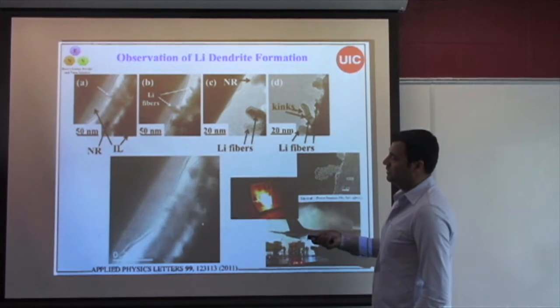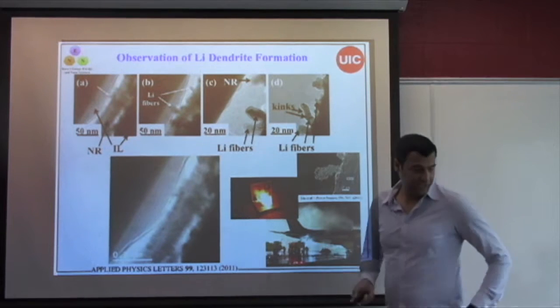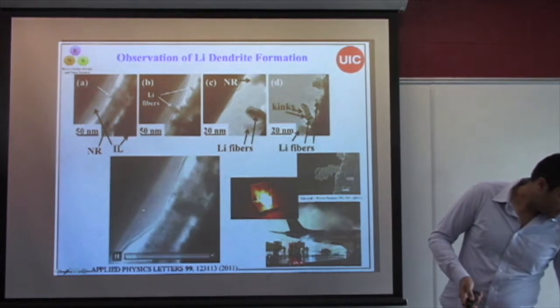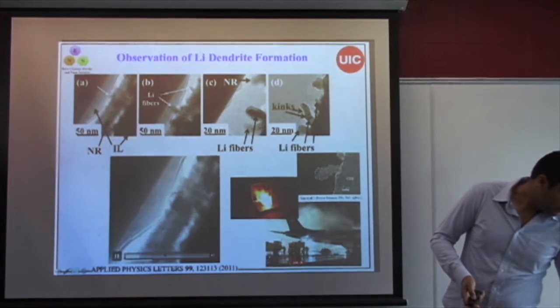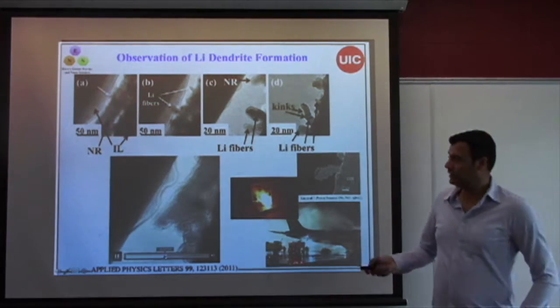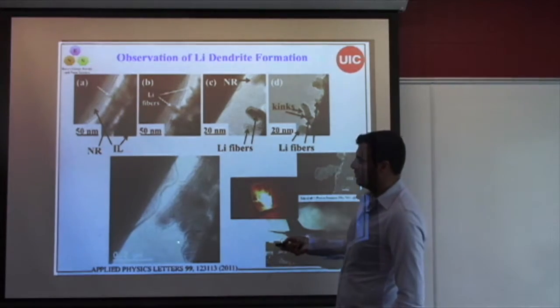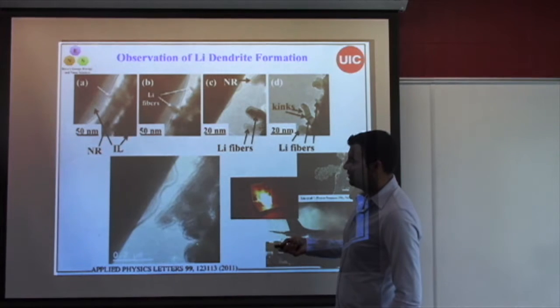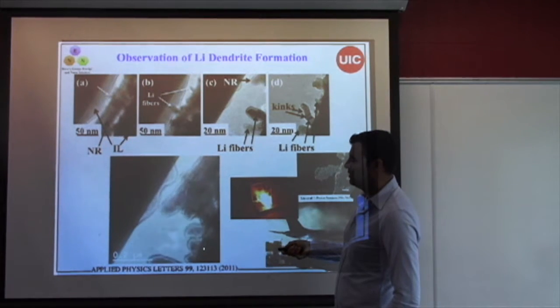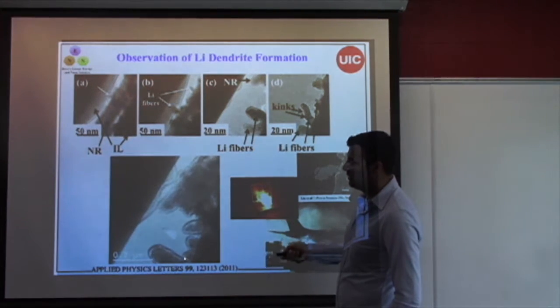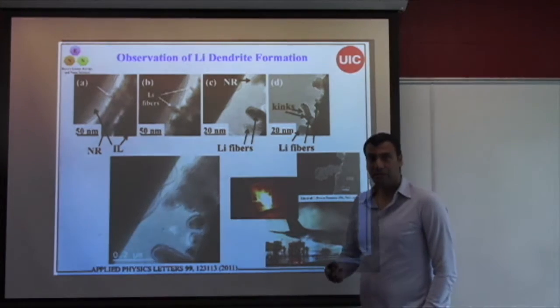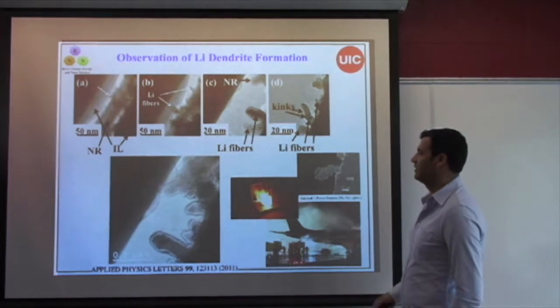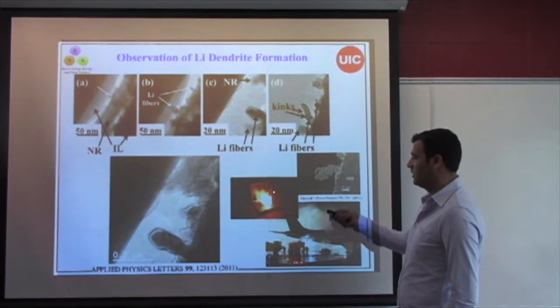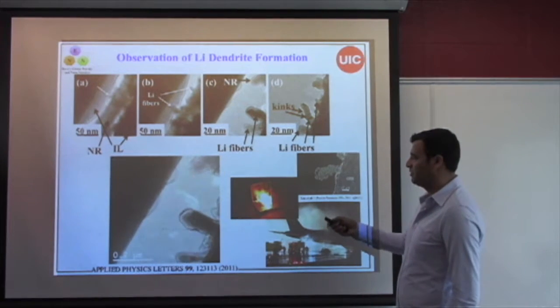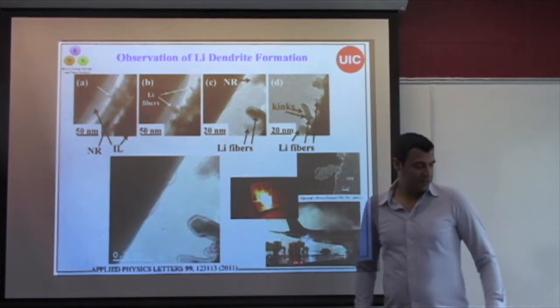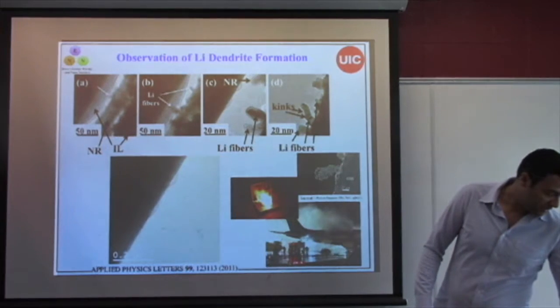We can study the dendritic behavior of electrodes using in situ TEM. It will give you a lot of information about the kinetics, the growth of the system, and what can be done to suppress the progression of these lithium dendrites, which has a lot of application in terms of prevention of failure and thermal runaway.